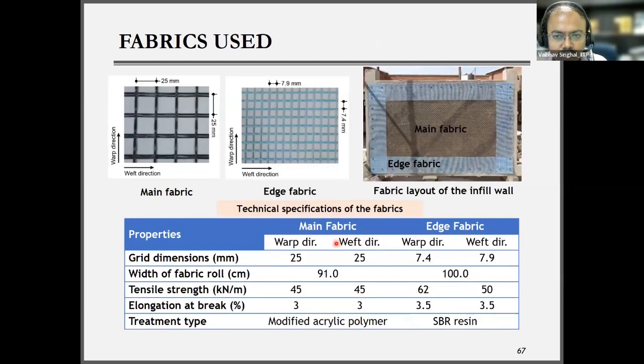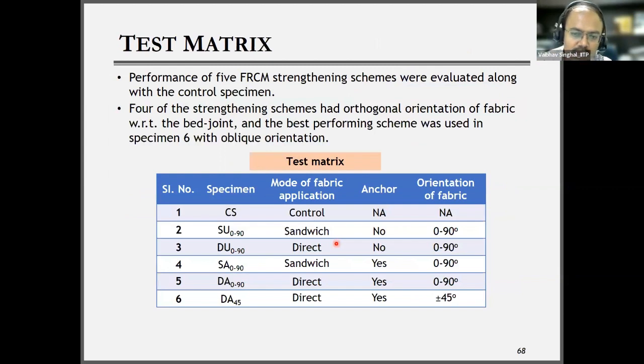So let me show you the test matrix. Yes, so this is the test matrix. Total there were 6 specimens. First was the control. There was no strengthening, but it has a plaster or mortar. Then the second one is the sandwich mortar, no anchors. Then the direct one with no anchors. Then again the sandwich with anchors and the direct with anchors. And then we tried another one where the fabric is placed at an angle of 45 degrees. In all other 4 specimens, from 2 to 5, the fabric was placed at 0 and 90 degree orientation.